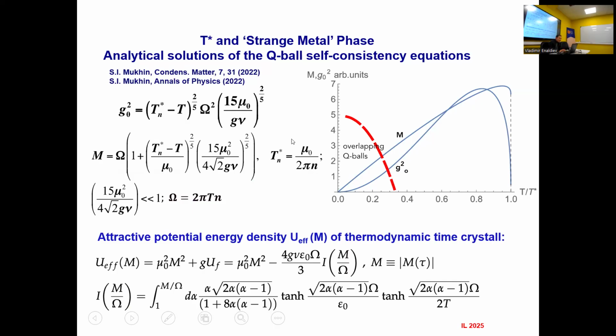But as we have seen, the amplitude of the Q-ball deformation, spin or charge density deformation, starts from a finite value, because we have seen that the Mathieu equation otherwise doesn't have a second level appearing in the potential as well. So in that sense, the Q-ball transition is first order with respect to Q-ball amplitude and second order with respect to the superconducting condensate inside the Q-ball. That's very funny, actually.